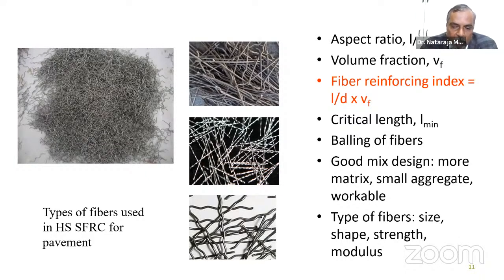How do you expect the mechanical properties of the concrete to improve? Definitely not. The ductility part can improve. The energy absorption capability, especially in the drooping portion of the stress strain diagram, can be better, but otherwise the compressive strength of the concrete is not going to increase. The mechanical properties of the concrete are not going to increase, especially when you go for low modulus fiber or fibers which are of low strength when compared to steel or carbon fibers. So this is just a small introduction, because today these types of fibers are also being used in pavement concrete.